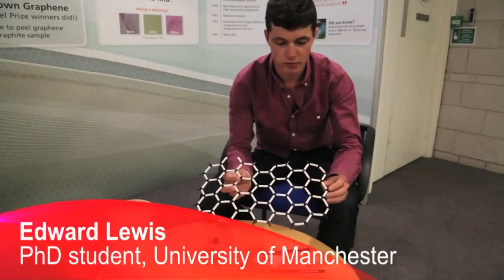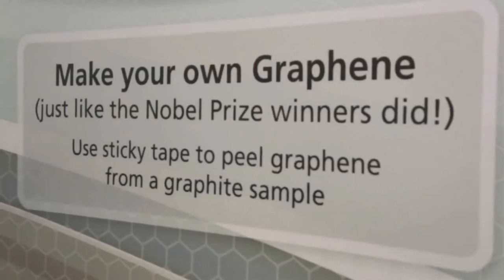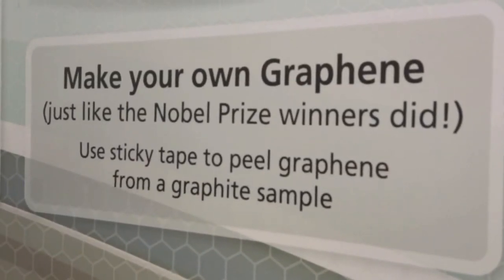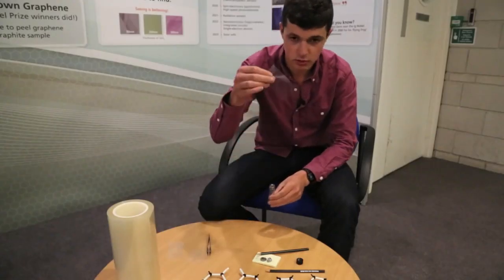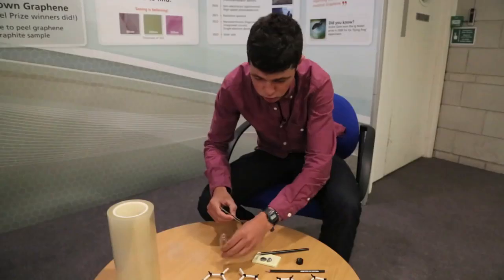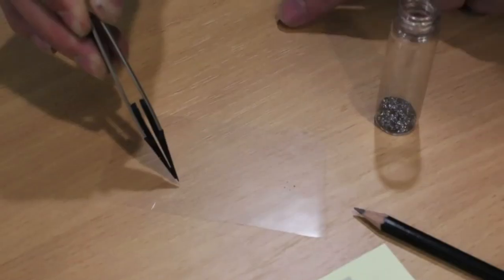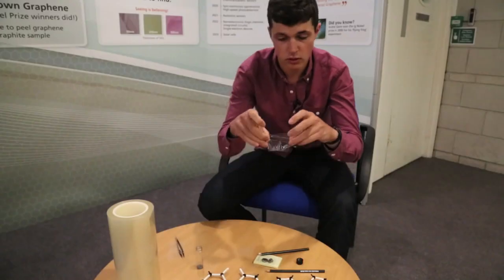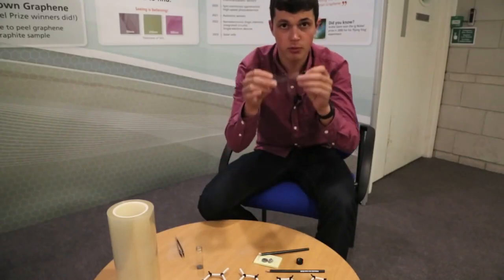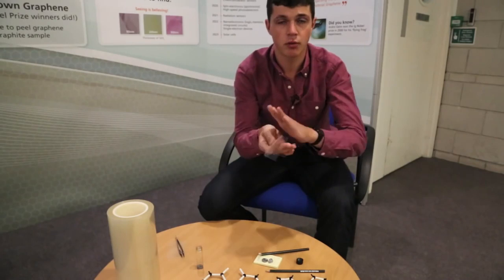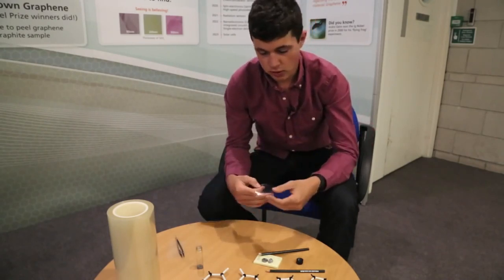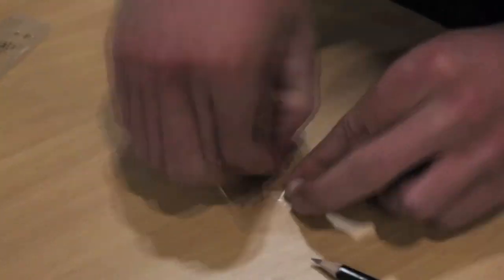How do we go from this layered material to getting a single layer, a layer that's only one atom thick, a layer of graphene? It's actually surprisingly simple. You need to use a simple piece of sticky tape, and we use the tape to pull the layers of graphite apart. And every time we pull the tape apart, we break our graphite up. We're cleaving it, pulling apart the layers. So the pieces of graphite we had in here originally would have contained many thousands of layers.